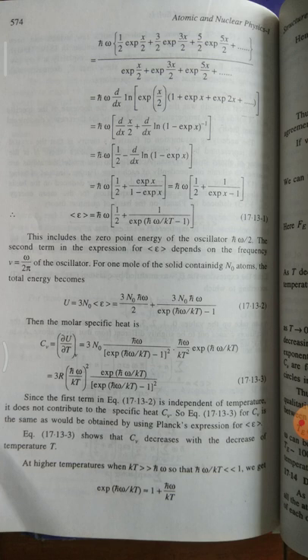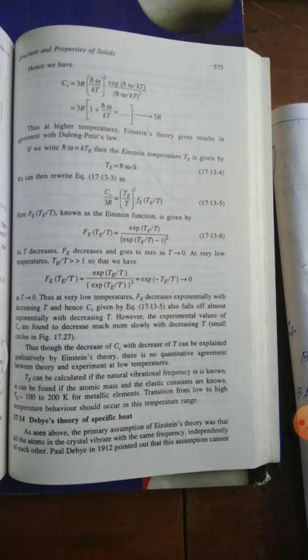Next, Cv decreases with the decrease of temperature T. At higher temperature, when kT is much greater than ħω, so that ħω/kT is much less than 1, we get exp(ħω/kT) approximately 1 plus ħω/kT. Hence we have Cv equal to 3R (ħω/kT) squared exp(ħω/kT) by (ħω/kT) squared, so Cv equal to 3R into 1 plus ħω/kT, which is approximately 3R.